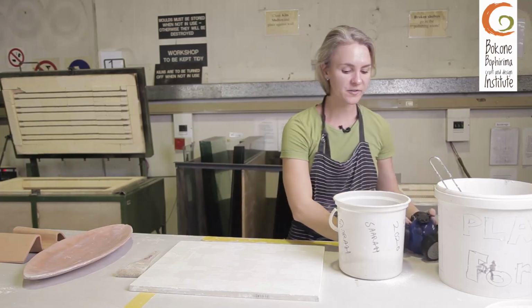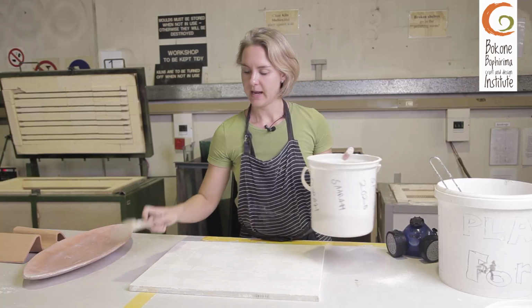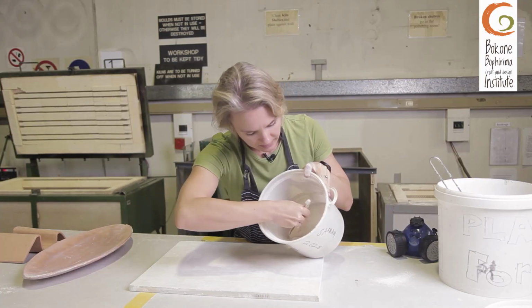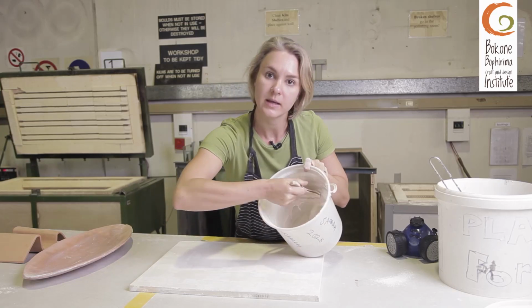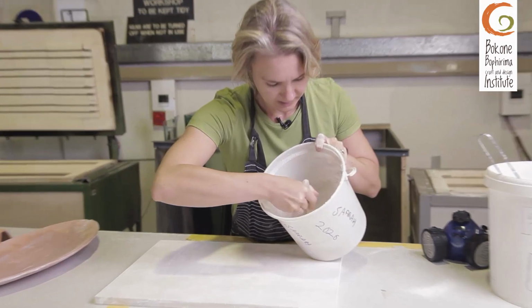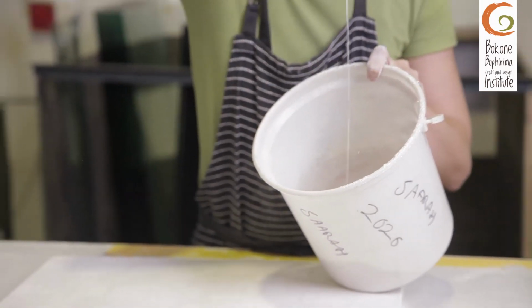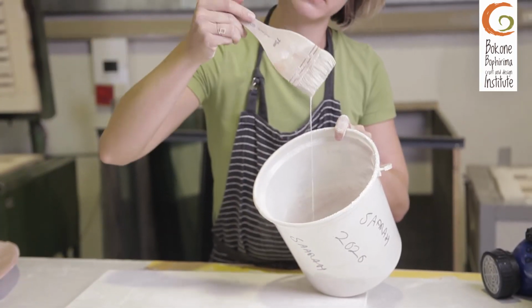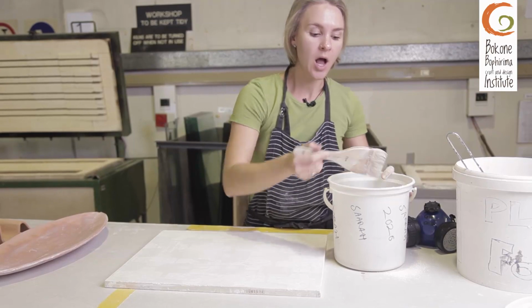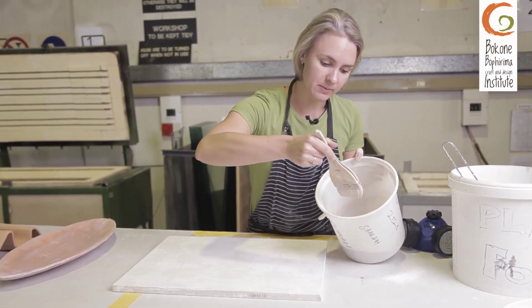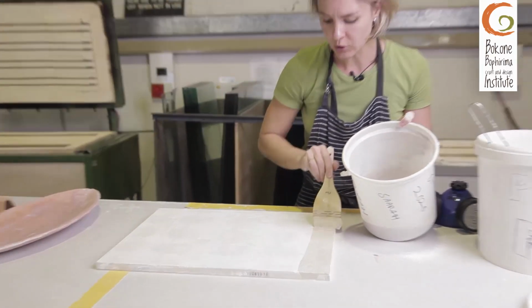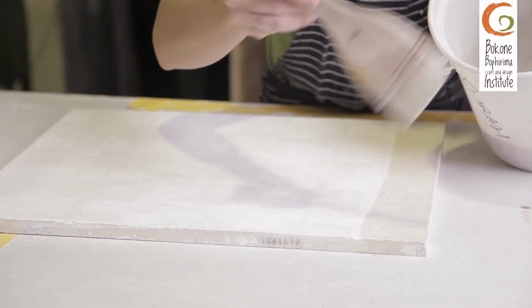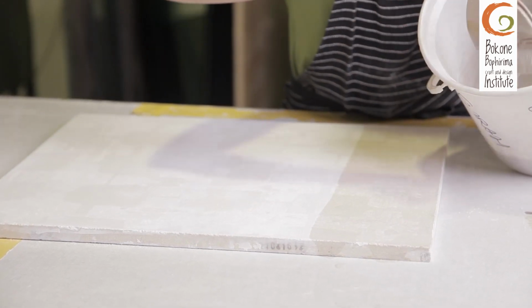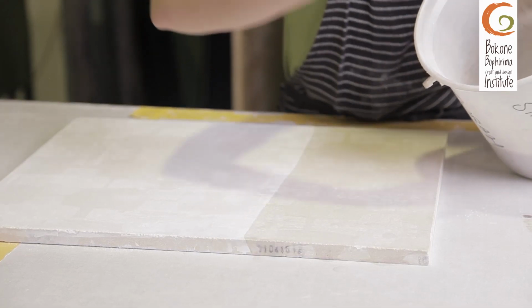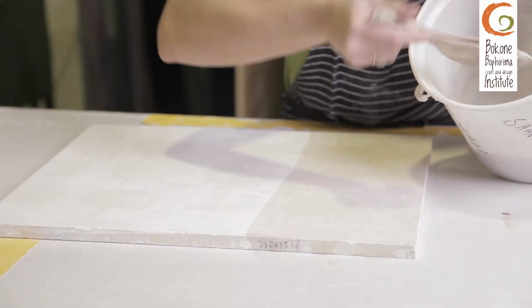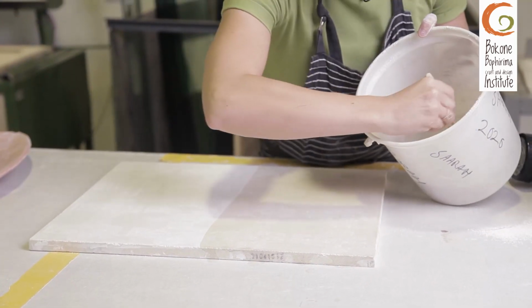Okay, I can take my respirator off because all the dust is gone, and I'm going to pick up my brush and mix the water and the plaster into each other. As you can see, it's a very watered down water and plaster mixture. This brush allows us to pick a lot of the water up at a time, to be able to make one brush stroke. Do not go back on itself, as it will lift the previous plaster that you have just applied. When you put your brush back down in your bucket, remember to go all the way to the bottom, because your plaster will tend to settle at the bottom of this mixture.